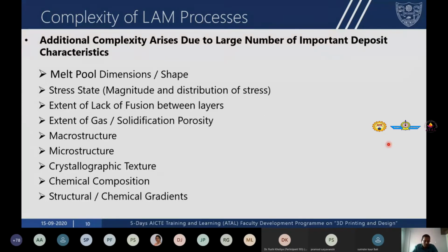Now, additionally, the complexity also arises from the large number of deposit characteristics that need to be understood. For example, we need to understand the melt pool because the melt pool controls the build conditions. So you need to understand the melt pool dimensions and shape. Then the residual stress is related to thermal gradients. We want to minimize residual stresses to decrease warping and distortion. Then we also want to look at the extent of bonding or lack of fusion between the layers that are deposited. In general, you see porosity in this process. The porosity can be gas-induced porosity or lack of fusion porosity.